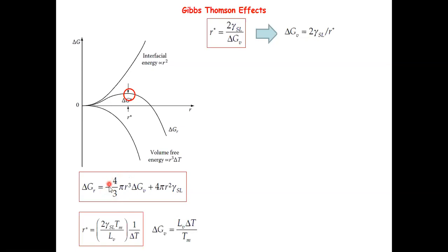And it's negative, which means that it's going to reduce the free energy of the system when you form the small nucleus. But we also said that if you look at the structure of this system containing the nucleus, there's an interface, right? That is typically associated with an increase of the energy, and that's going to give you an increase of the total free energy of the system resulting from the existence of the interface. This is going to be proportional to the interface energy, which is the energy per unit area, and then the total surface area of that small nucleus, if you assume this is a sphere in 3 dimensions, right?